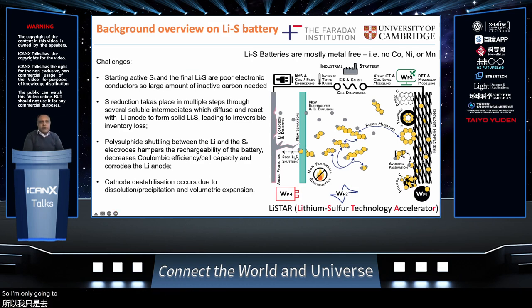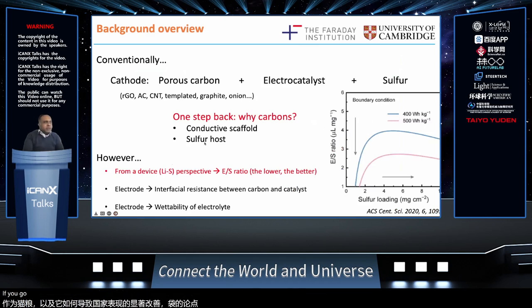So I'm only going to talk about how we've replaced the porous carbon with metallic 1T MoS2 as cathodes, and how that leads to dramatic improvement in the performance of state-of-the-art lithium sulfur batteries. So if we go back one step, why do we use carbons? As I said, the carbons act as the conducting scaffold for the sulfur. Because the lithium sulfur battery is based on these different reactions between lithium and sulfur and the sulfur reduction reaction, there's typically a catalyst that is added to the porous carbon. And then the sulfur is loaded onto the electrode.